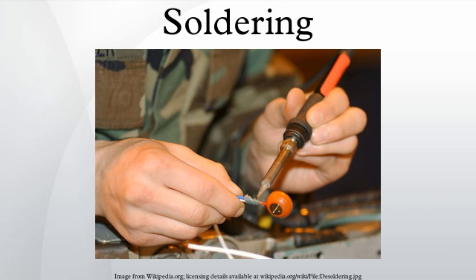A dry joint occurs when the cooling solder is moved, and often occurs because the joint moves when the soldering iron is removed from the joint. An improperly selected or applied flux can cause joint failure. If not properly cleaned, a flux may corrode the joint and cause eventual joint failure. Without flux, the joint may not be cleaned, or may be oxidized, resulting in an unsound joint.